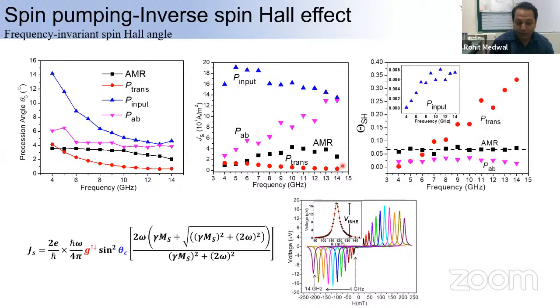So when we measure the spin current from the AMR and the voltage from the VISHE, and put them together, what we clearly observe is that the spin Hall angle is frequency invariant only from the AMR effect. This is also frequency invariant from the power absorption, but the absolute value is not correct. The absolute value, plus the behavior of the spin Hall angle in platinum, is only true when we are measuring the signal from the AMR method. So this was a quite good discovery, where we were able to show that for a longer range of frequency, we can have a frequency invariant spin Hall angle in the platinum.